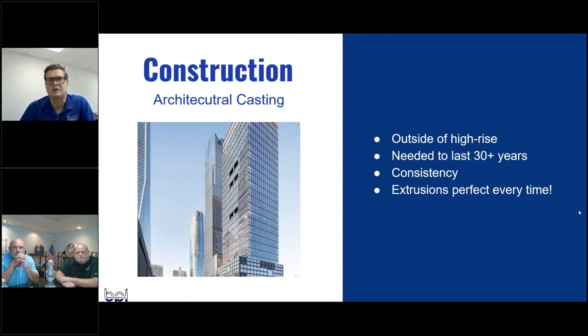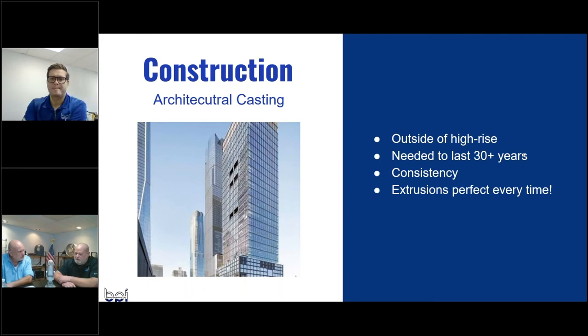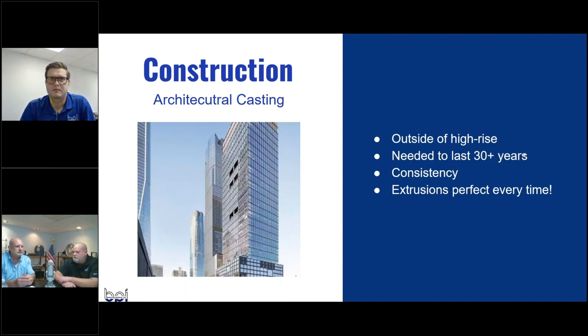Questions came in: what is the minimum draft angle, and can you explain draft? The minimum draft angle is three degrees for functionality. When you get into finishing, you want to look at five degrees or more to maintain tooling and coatings. Draft is included on each side — you cannot cast a true vertical wall in any casting system or process, so it's going to have draft all the way around.